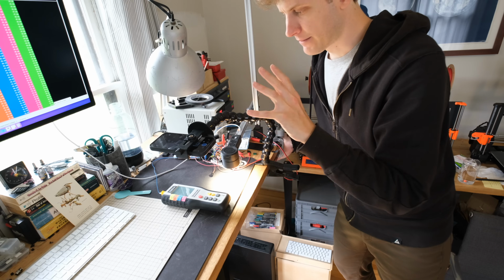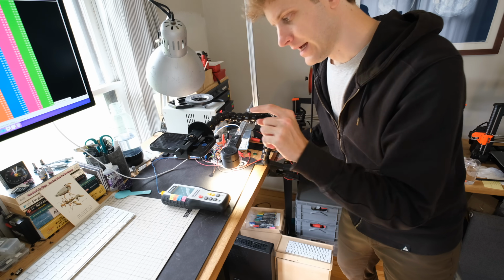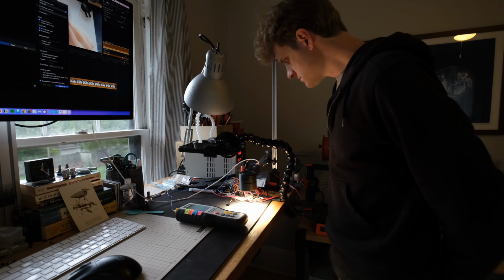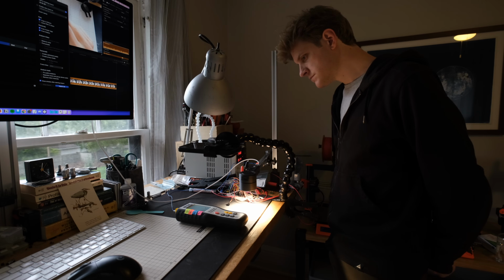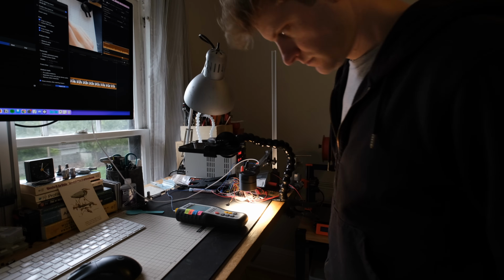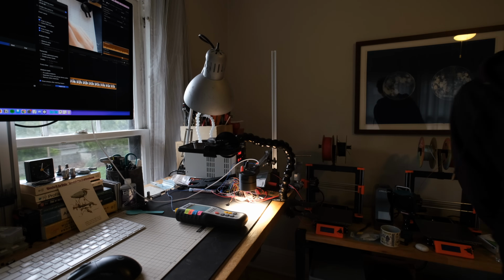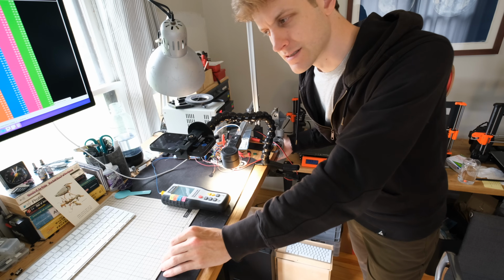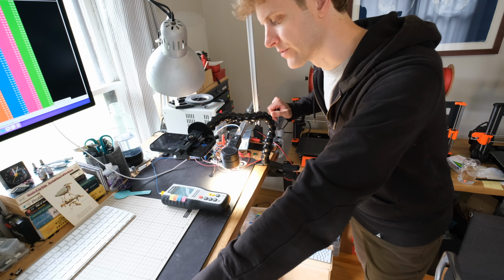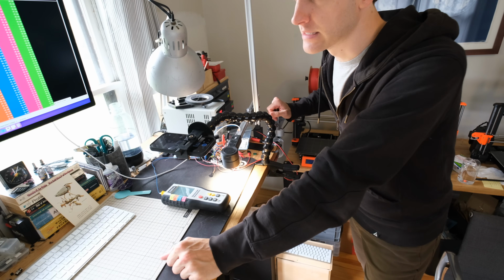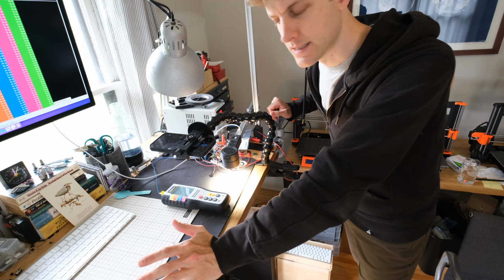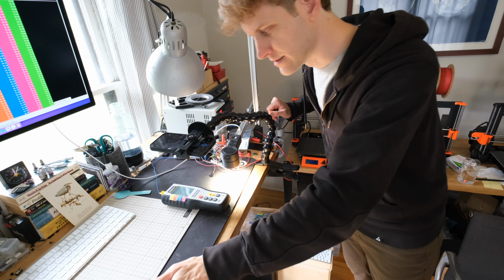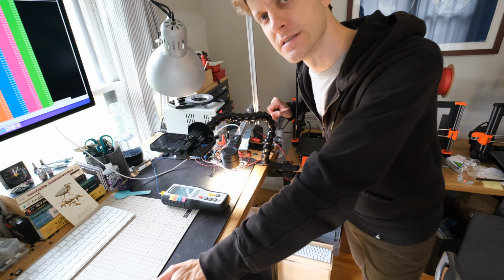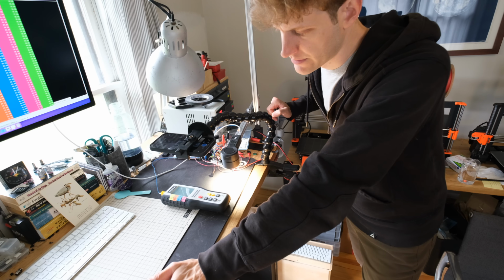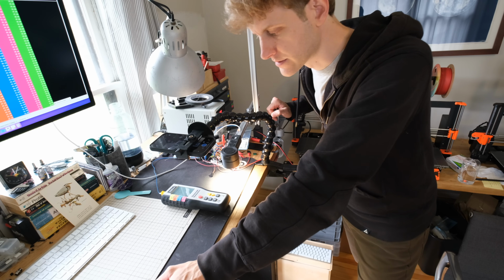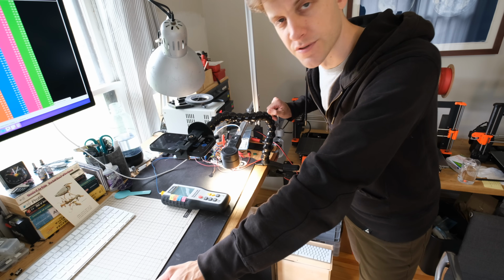So I'm running it at max brightness for 1 hour and taking a photo of the thermometer every 30 seconds. And after it finishes, I can do a little breakdown of the temperature over time and see where the max temperature is. So hopefully we never hit that temperature threshold, but we'll have to wait for the data and see. Right now, I'm 13 minutes in and the housing temperature is 35.7 degrees Celsius and the room temperature is about 25 degrees Celsius. So yeah, we'll see where we end up.